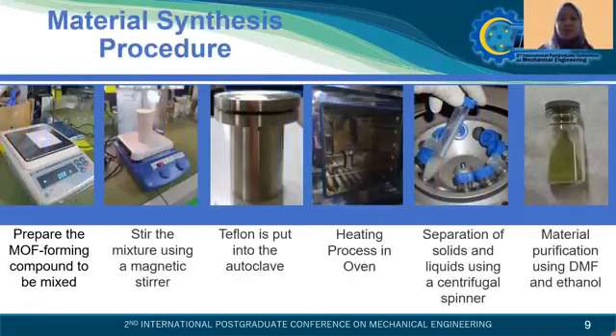And here are the steps of our synthesis procedure. After we stir the mixture using a magnetic stirrer, we put it into the Teflon, and after that we do some heating process in the oven, and we do some centrifugation to separate the solid and liquid.